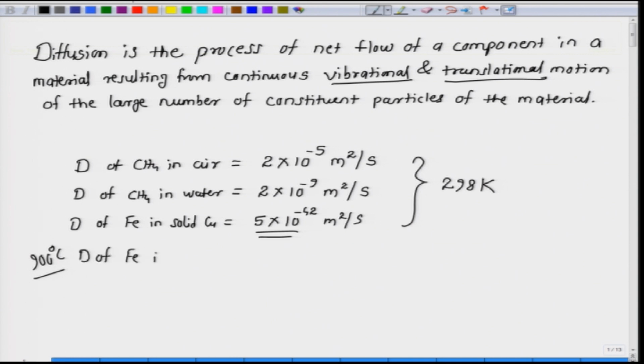So, diffusivity of iron in copper comes out to be around 10 to the power minus 14 meter square per second. So, even at 900 degree centigrade, diffusivity in solid copper is around 5 orders of magnitude slower than diffusivity of methane in water, and it is 9 orders of magnitude slower than diffusivity of methane in air, right. So, if we talk in terms of the diffusion distances, which is easier to see.